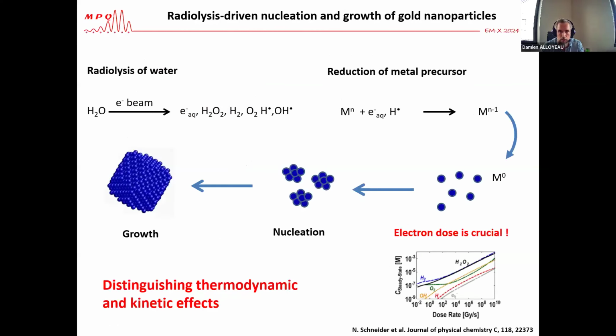So when you study the growth of nanoparticles, usually you are using the radiolysis of your solvent by the electron beam. If you take the example of water, you split the water molecule into various chemical species and radicals. And among those chemical species, you have highly reductive agents like aqueous electrons or hydrogen radicals that can reduce your metallic precursor to the metallic state and induce the nucleation and growth. And what is known for a long time now, because radiolysis is a well-known process, is that the steady state concentration of those reducing agents depends on the electron dose rate, meaning that we can use the electron dose rate to control the growth speed, which allows you to control your reaction kinetics and observe the effect of this reaction kinetics. So that's what has been done for a long time.